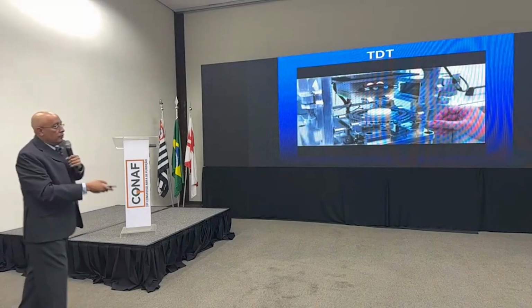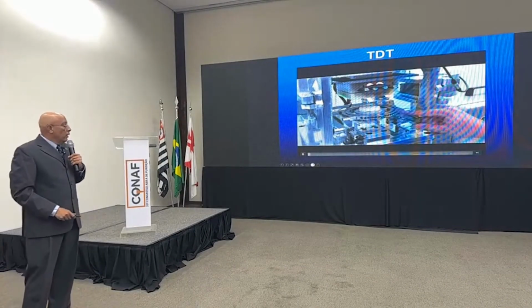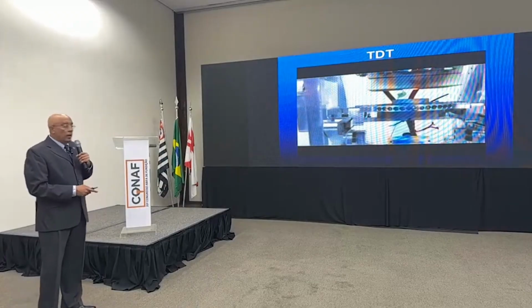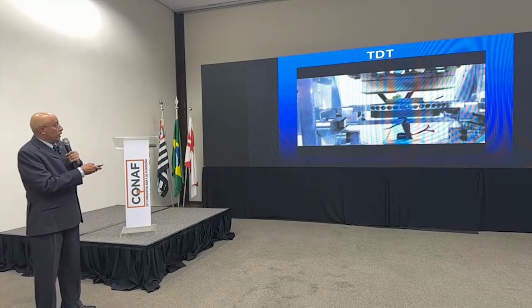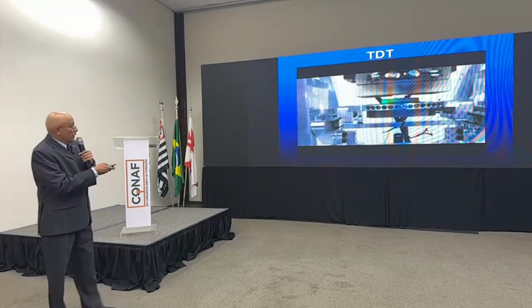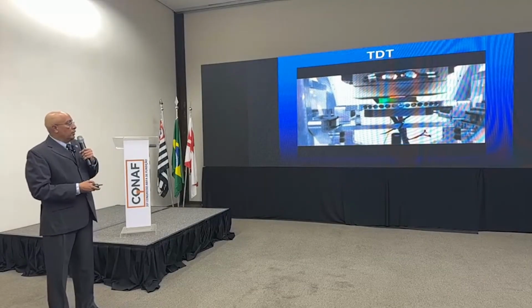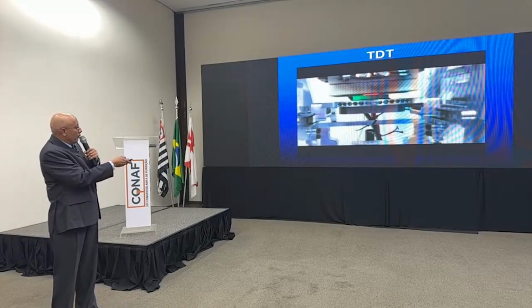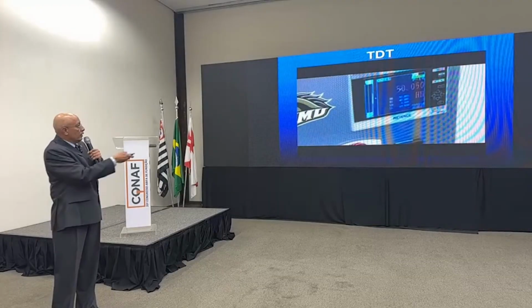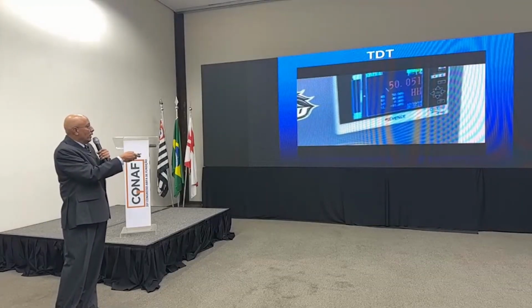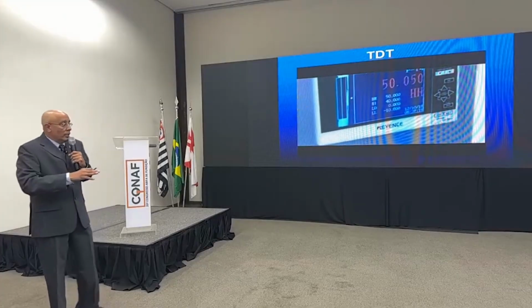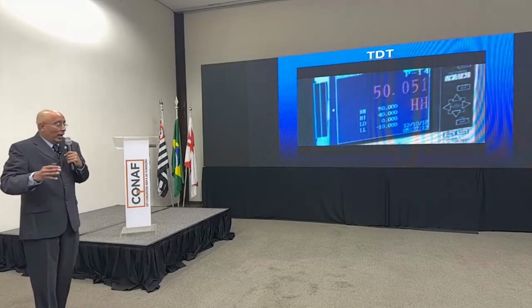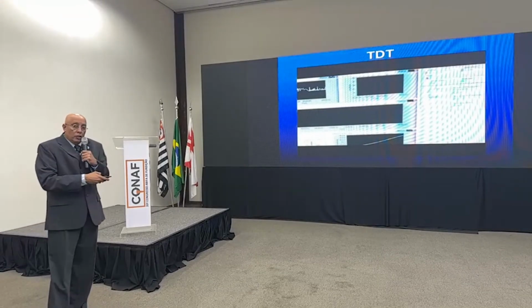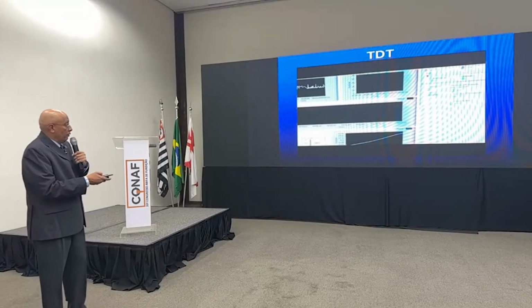So there's a video here to show you. Okay, so the cookie is loaded on a gimbal and it's brought in direct symmetrical contact to the hot surface. That is the alloy temperature superheat, and we are tracking the temperature on the back side and at the hot surface. The cookie is nominally 50 millimeters in diameter, so we could track in real time its movement radially as well as axially. So what we are trying to do is get data 3D for temperature and dimension of the cookie in this test.